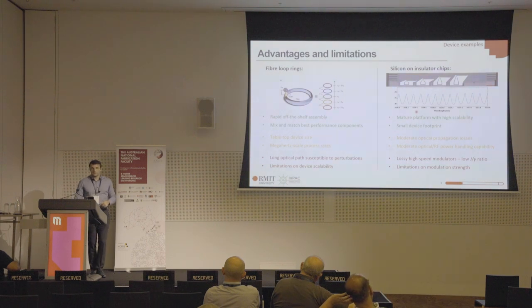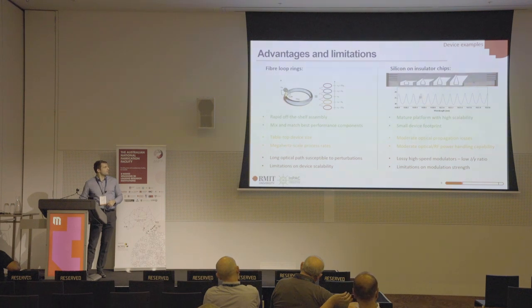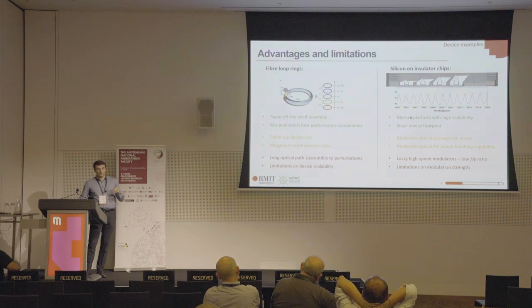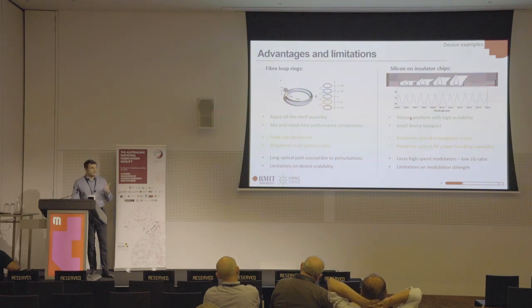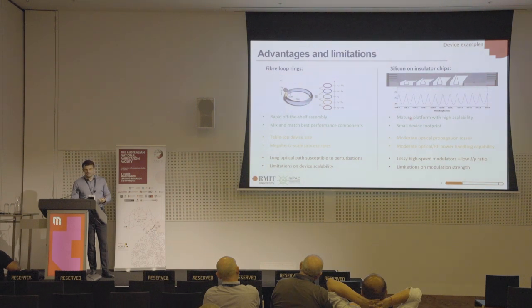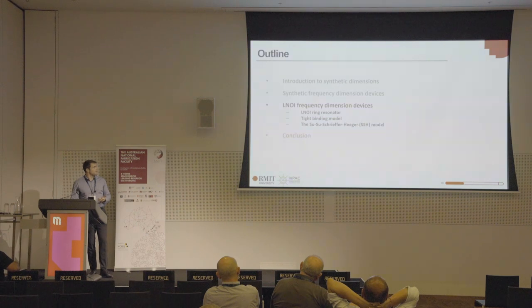My introduction to this field was creating a silicon-on-insulator, CMOS-compatible ring resonator as a synthetic frequency dimension device. We devised a design in Japan, sent it off to a foundry, and got it back fabricated. It worked as well as it could have, but the key issue is that high-speed modulators in silicon are not particularly efficient and have quite large losses.